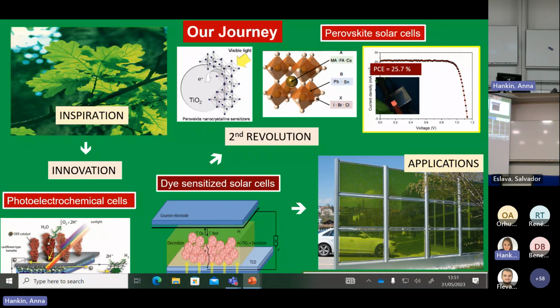The dye-sensitized solar cell is actually a sensitized mesoscopic junction. It's a monolayer sensitized. We can use a monolayer of dye or quantum dots. However, it's a single layer sensitized. The trouble with that concept is if you do it on a flat junction surface, then the current will be very, very low. So you have to get 1,000 times the surface enhancement without getting the back reaction 1,000 times that. This mesoscopic concept worked out, against many critical and skeptical views at that time.